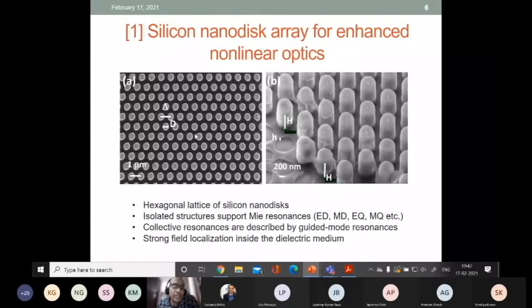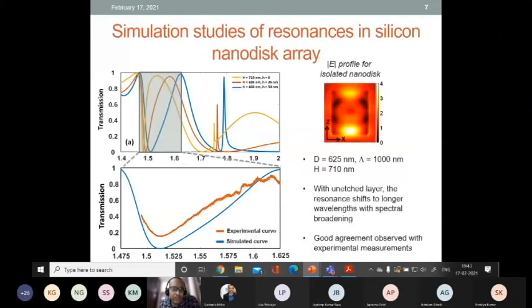A better way to describe these kinds of resonances is based on guided mode type resonance effects, where light is guided into an effective waveguide media and then selectively coupled out at characteristic frequencies, where it can again constructively or destructively interfere with the specular reflection components, creating very interesting resonance effects. That's what we are also trying to leverage to create resonant metasurfaces.